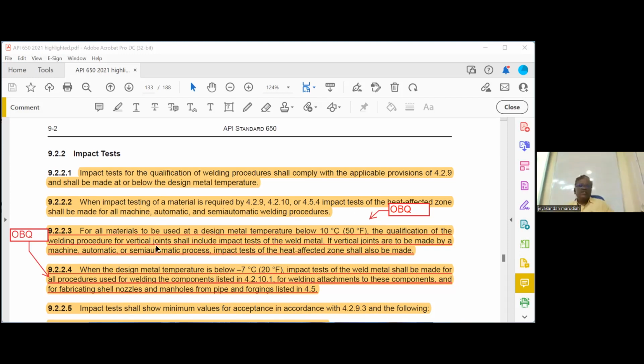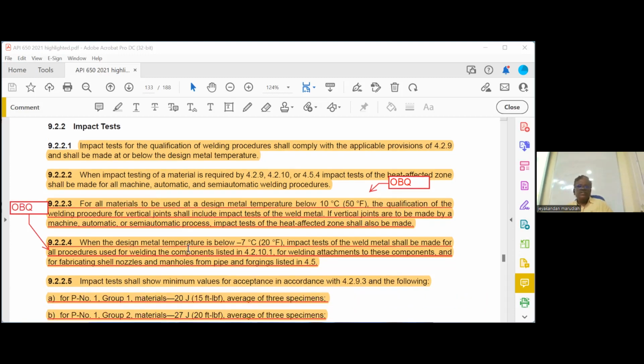The qualification of welding procedure for vertical joints shall include impact test of the weld metal. If vertical joints are to be made by machine automatic, impact test of the heat affected zones also, that is open to question. When the design metal temperature is below 20 degrees Fahrenheit, impact test of the weld metal shall be made for all procedures used in the welding. Suppose if it is less than 20 degrees Fahrenheit design temperature, for all procedures, whether it is a horizontal weld or vertical weld, we have to do impact test. It is only for procedure impact test.